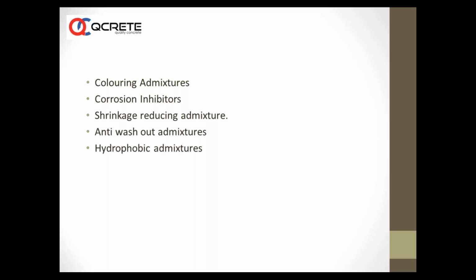You have hydrophobic admixtures, where you need to make the concrete pores repel water. The concrete should be almost impermeable, and you increase impermeability by incorporating materials like calcium stearate. This kind of material coats the capillary pores and provides hydrophobicity, meaning water repellency. The only problem is they do not work where there is a head of water, where water pressure is exerted on the structure.